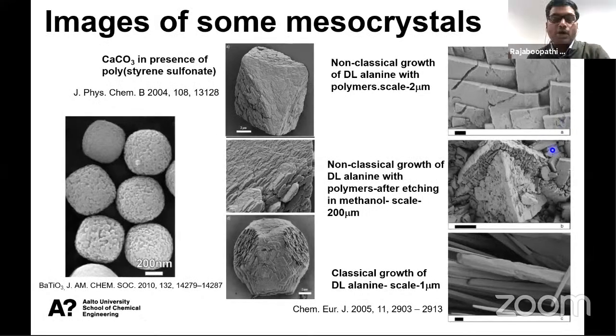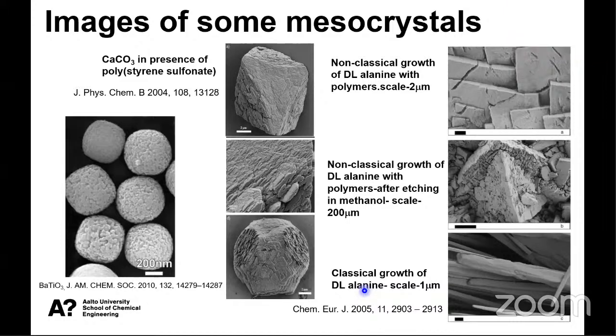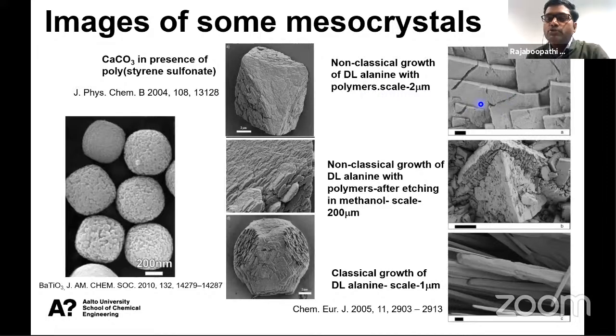And this is the case of organic crystals. This is DL-alanine, an amino acid. The amino acid has a permanent dipole moment to separate the nanoparticle units. And people also use some polymers to produce these DL-alanine mesocrystals. This is the mesocrystal of DL-alanine. To see what is inside, they used some etching. They dissolved it in methanol and reported this SEM image where you can see clearly the attachment of particles.